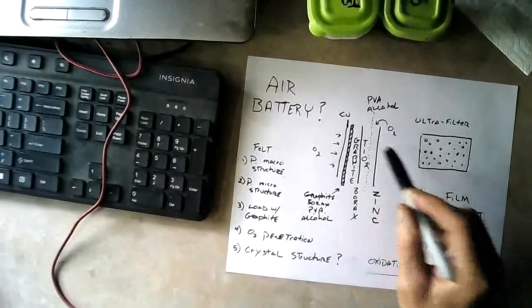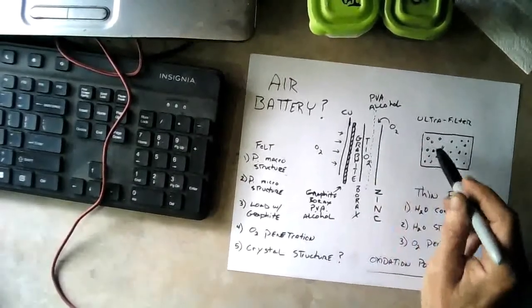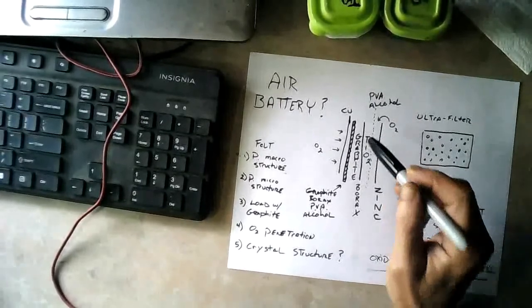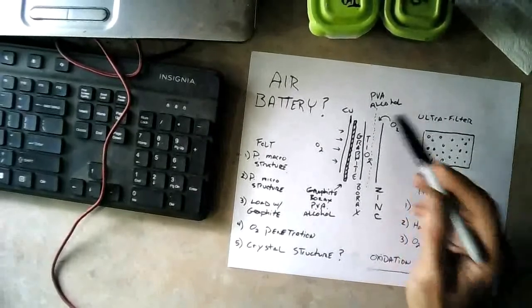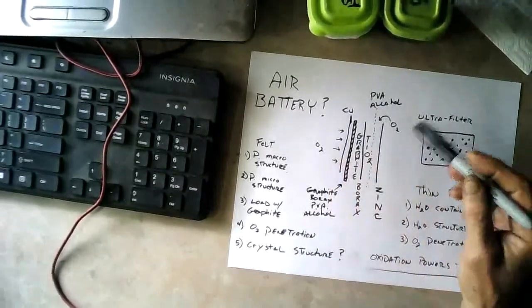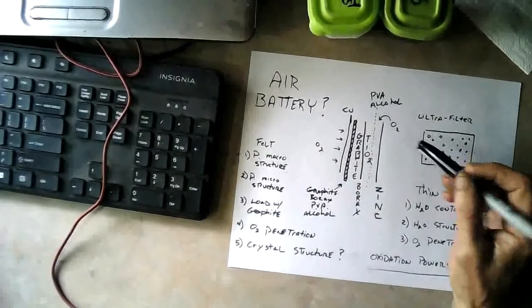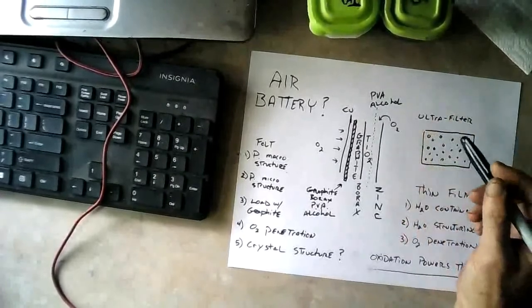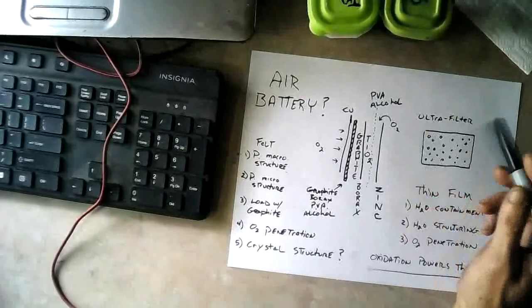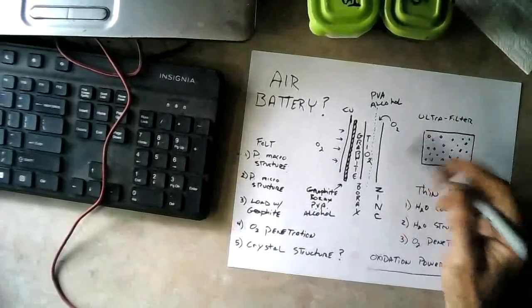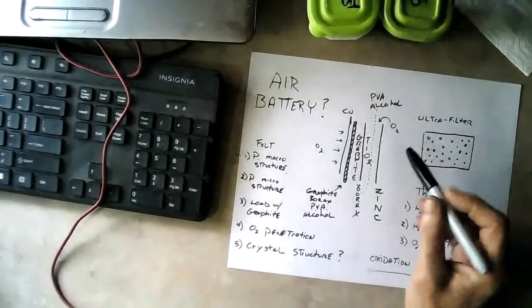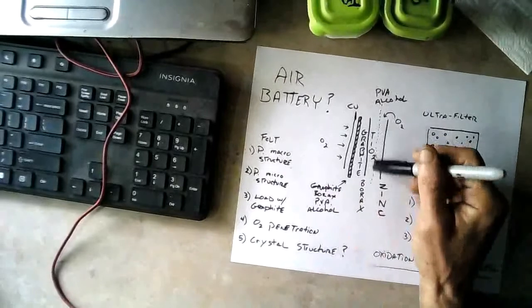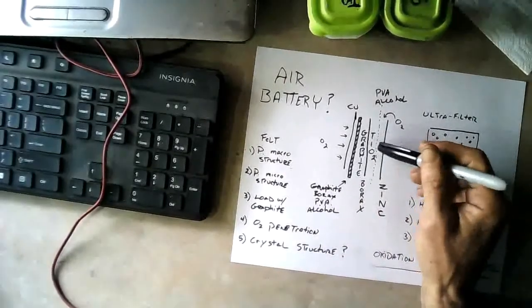In our case, it's to let oxygen through the membrane so it can oxidize the zinc here and provide power for the cell. I believe this is an air battery. I've suffocated the cell twice and revived it both times by opening up the bag and letting air back in. I've drowned the cell by submerging it in water, and that killed it. I took it out of the water and it revived.